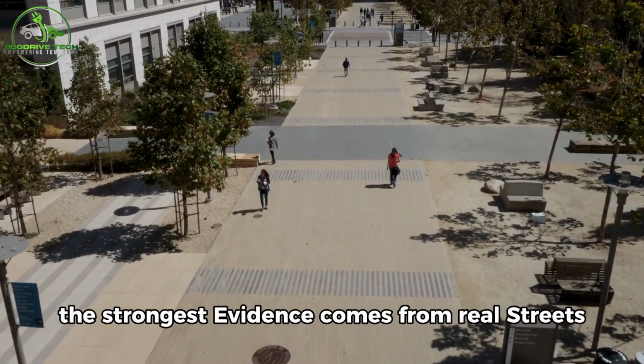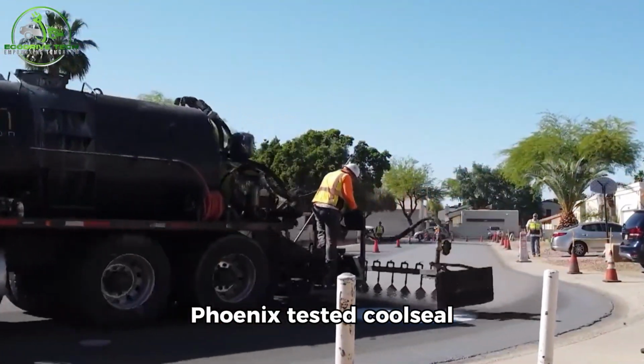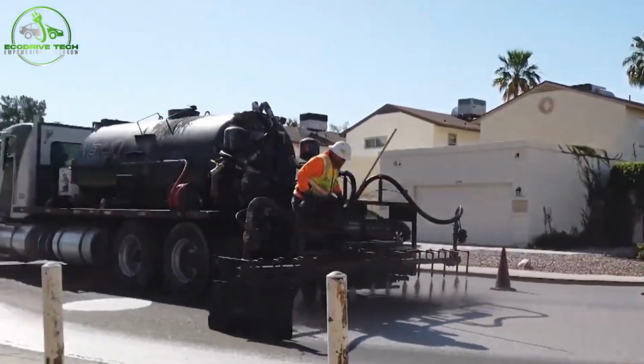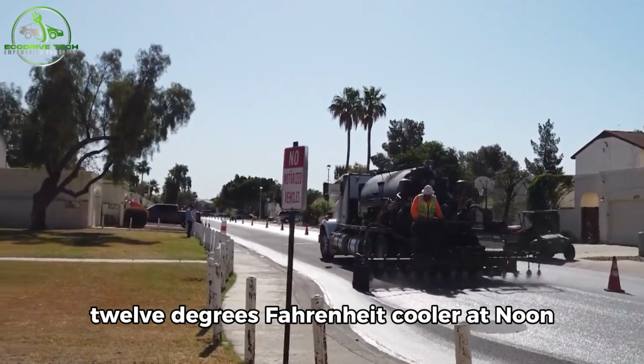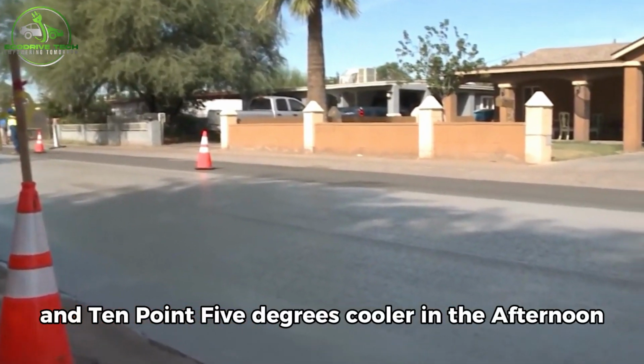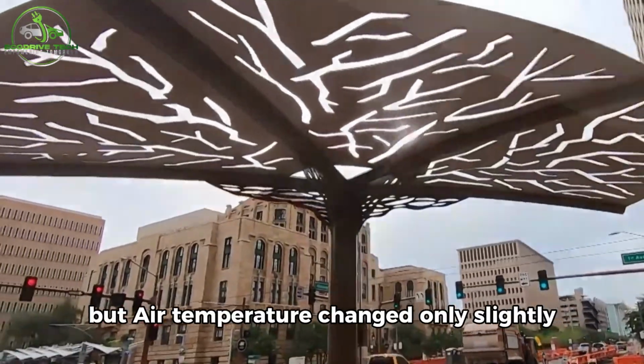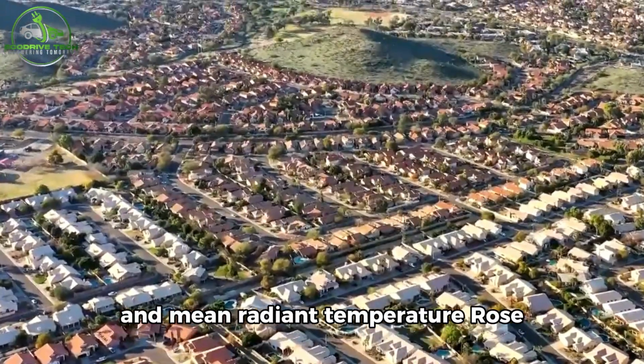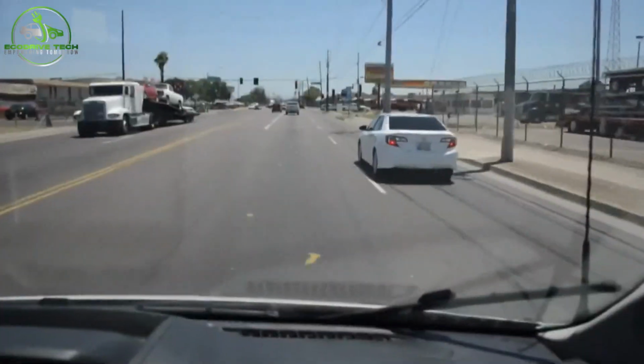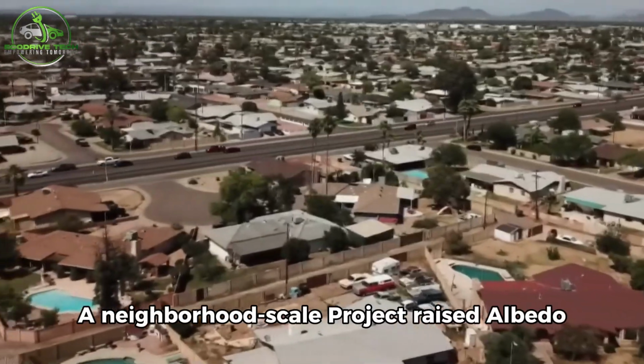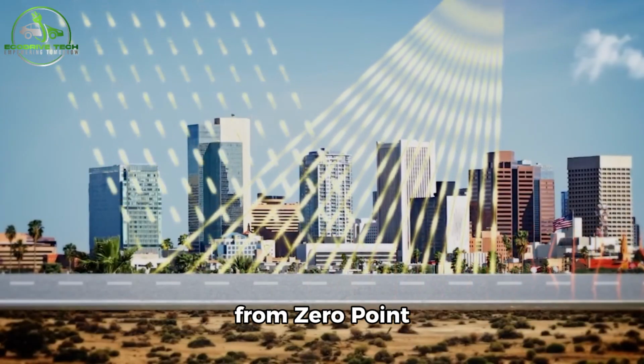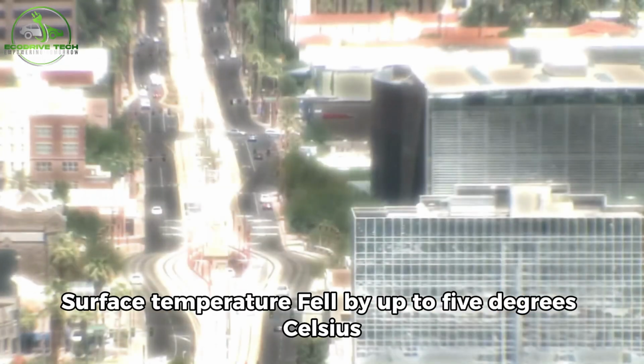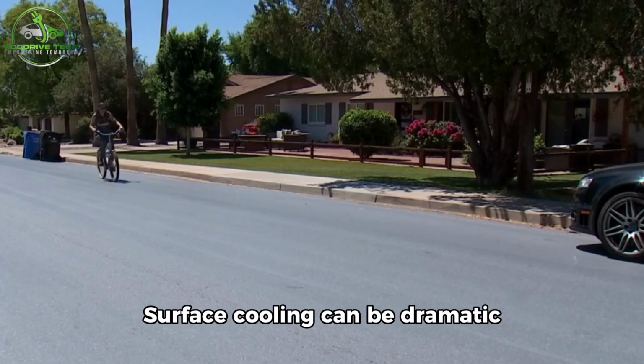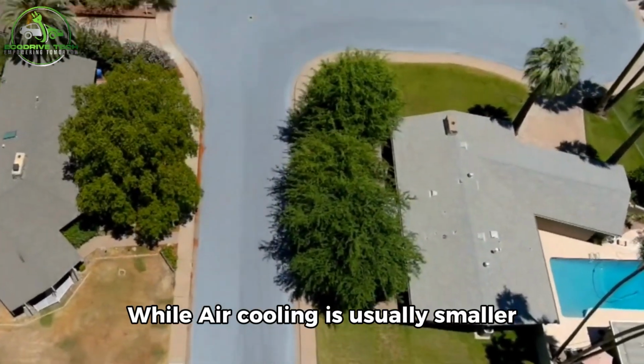The strongest evidence comes from real streets. Phoenix tested Cool Seal on 36 miles of residential roads. The pavement averaged 12 degrees Fahrenheit cooler at noon and 10.5 degrees cooler in the afternoon. But air temperature changed only slightly, and mean radiant temperature rose about 5.5 degrees Fahrenheit. In Covina, near Los Angeles, a neighborhood-scale project raised albedo from 0.08 to 0.26. Surface temperature fell by up to 5 degrees Celsius, while near-surface air temperature fell. That proves the key lesson. Surface cooling can be dramatic, while air cooling is usually smaller.